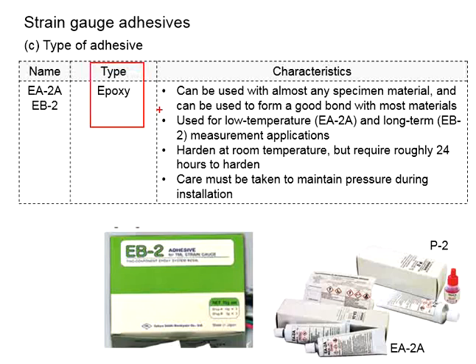Next one, it will be the epoxy. You have EA, 2A, and EB2. This one can be used with almost any testing material, as it ensures a good bond with most of the material. EA2A is used for low temperature, and EB2 is used for the long-term measurement application. The epoxy type of adhesive hardens at room temperature but it requires longer time, which is roughly about 24 hours to harden. Care must be taken to maintain the pressure during the installation, and theoretically, pressure should be applied throughout that 24 hours until it is fully hardened.